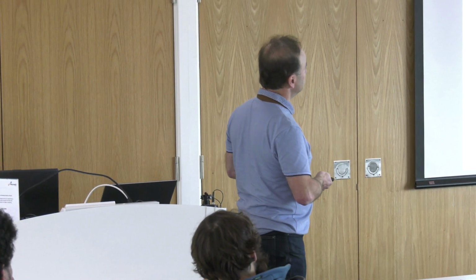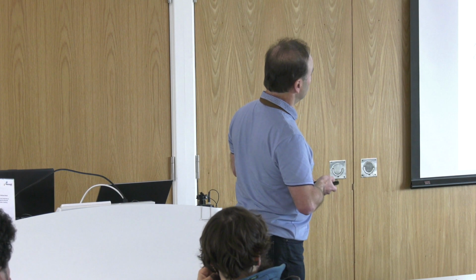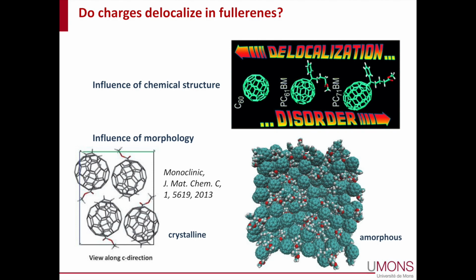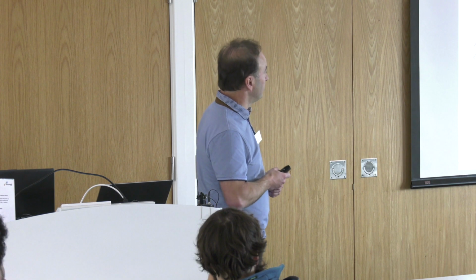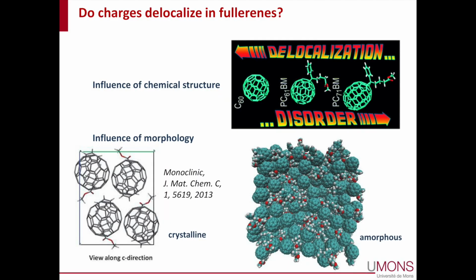So in organics, the other ingredient I would like to talk about is this quantum mechanical interaction between the molecules that drives delocalization. And the type of system that we looked at to model this are fullerenes. Fullerenes, in principle, are very nice compounds to tackle that problem. They are extensively studied for organic solar cells, in part because of their high symmetry, and that should in principle sustain high delocalization, because now you have not only a large geometric connectivity between a molecule and its surrounding because of the spherical symmetry, but also a large electronic connectivity. And so we wanted to quantify how much a charge that we inject into those fullerenes would be delocalized if we look at crystalline versus amorphous structures, or if we look at unsubstituted fullerenes with respect to the soluble version of the fullerenes.